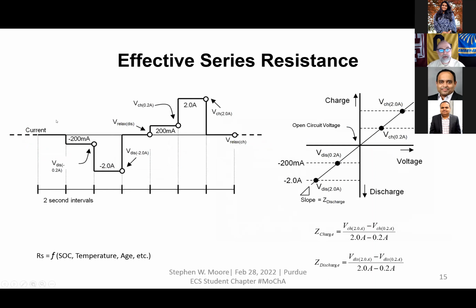In this example, I apply a current of maybe minus 200 milliamps, and then I perform a step at minus 2 amps, which is an order of magnitude higher. And then I measure the voltages at these points. Then I apply a positive 200 milliamps and a positive 2 amps, and I measure the voltages at those points. And then I can plot my voltage versus current. So here's my minus 2 amp point, my minus 200 milliamp, my plus 200 milliamp and my plus 2 amp. And then I can draw a line through it and find the slope of this line.